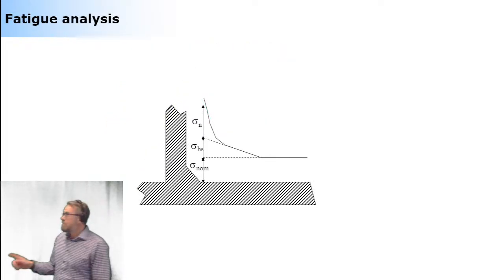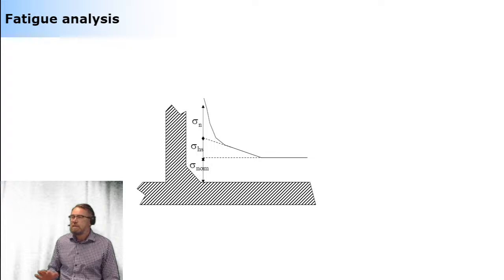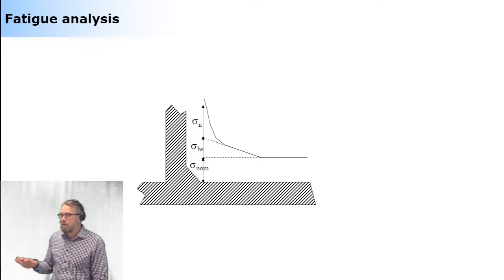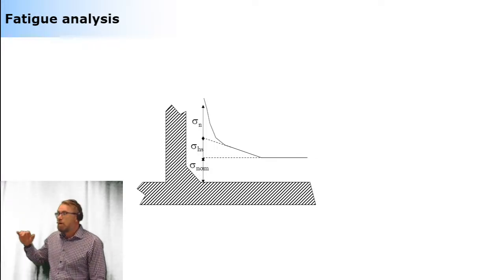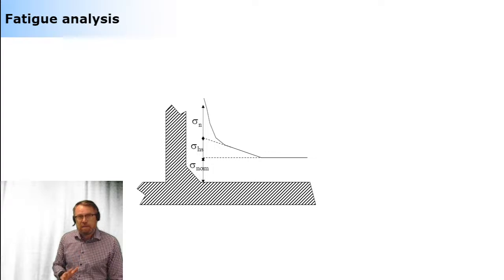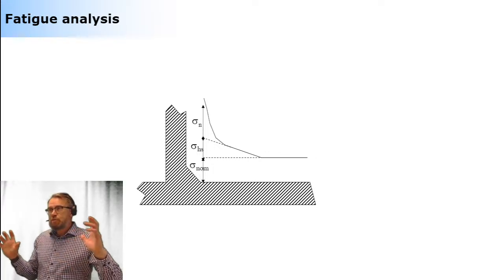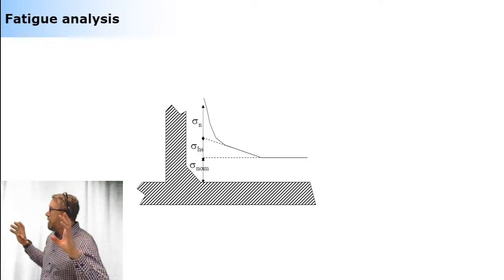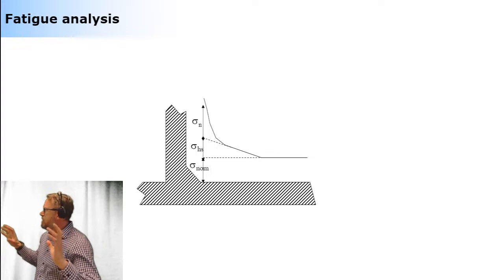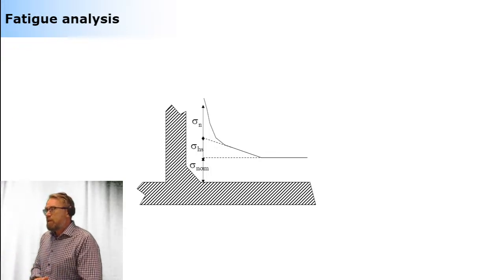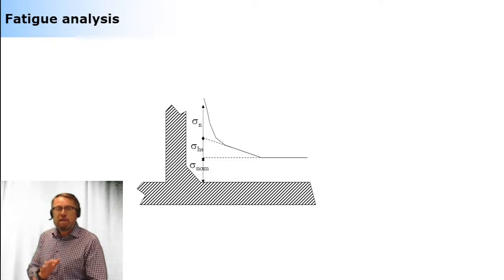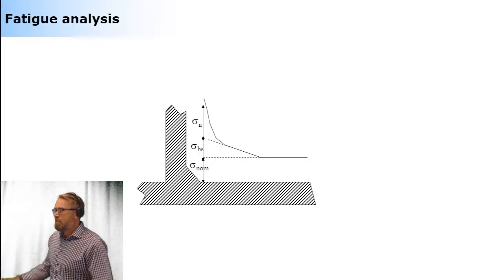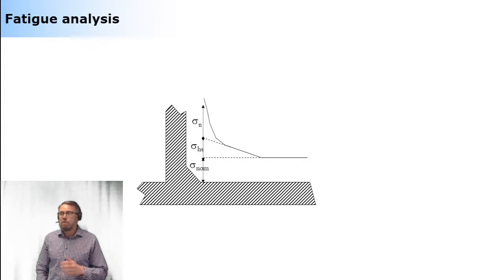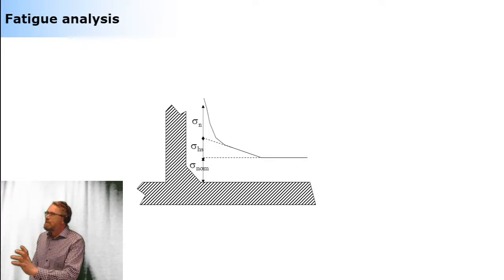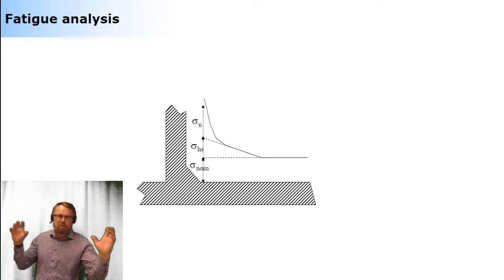All right. This is what I meant about the local high stresses, because of the geometrical nonlinearity, this non-smooth geometry. If you really look at the stresses because of the geometrical change, they are typically higher than the stresses that keep the structure in an equilibrium position. And these stresses are simply because of this very local detail. These very local details are something you need to be very careful with, because the fatigue prediction methods are based on the level of stresses you're able to get. And if you're using multi-body models to get the stress histories, you get the lowest accuracy stresses in terms of the local details. Those are the equilibrium stresses, the ones that keep the structure in equilibrium position.